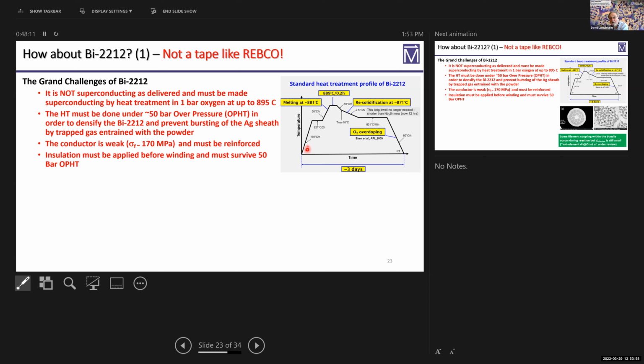And so we have this kind of complex heat treatment. When it melts, it ejects oxygen from the structure. We then go through a very carefully controlled solidification process by which we get very sparse nucleation of the 2212 plates from the melt. And we allow this sparse nucleation to gobble up misoriented grains. And so the reason that this works as a round wire conductor is that we're capable of generating a biaxial texture. It's not as good as the biaxial texture in REBCO, but it is pretty good, purely by thermal methods. And so this is how we get the very high current density.